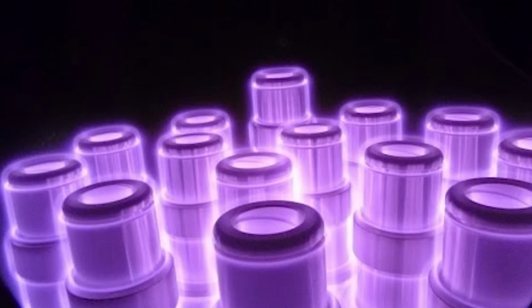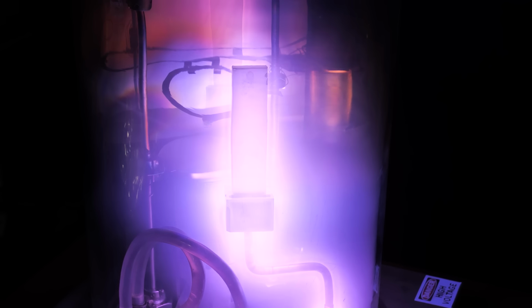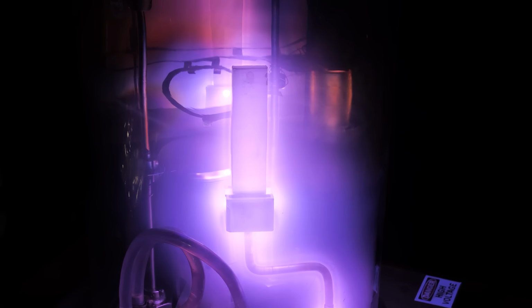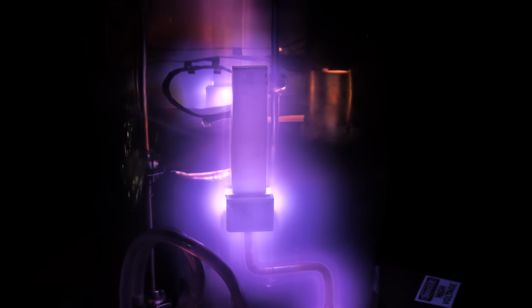We tried this many times before realizing that our vacuum system is actually too good. We built it for doing plasma-based metal coating, and for that you want an incredibly deep vacuum. But for plasma nitriding, apparently you need much higher pressure. With vacuum chambers like this, you can gauge the pressure just by looking at it. If the plasma fills the entire chamber, the pressure is very low. But if the plasma is denser and hugs the metal, the pressure must be higher.